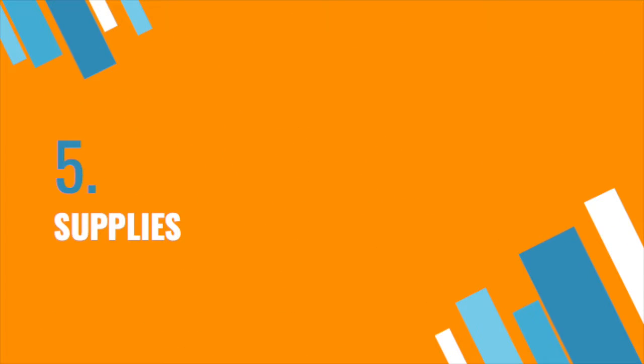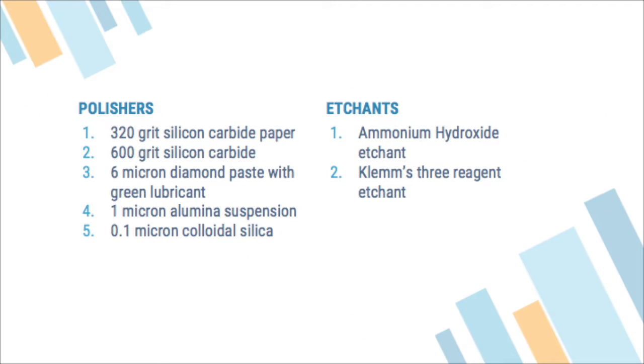For this experiment, you will need a series of platen polishers starting at 320 grit silicon carbide paper and progress through 600 grit silicon carbide, 6 micron diamond paste with green lubricant, 1 micron alumina suspension, and finish with 0.1 micron colloidal silica. After polishing, an ammonium hydroxide etchant as well as Klemm's three reagent etchant will be used.